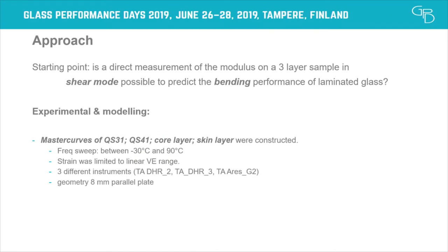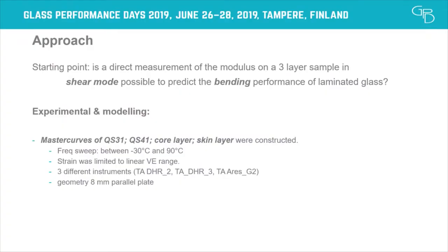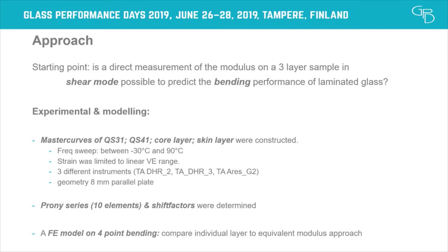We conducted experiments on three different DMAs because results can depend from instrument to instrument. There are some small differences, mainly in the transition point, even though all three systems are equipped with a convective oven providing identical temperature control. Geometry was an 8mm parallel plate. We then calculated PRONY series using 10 elements, determined the shift factor, and built a finite element model for four-point bending.